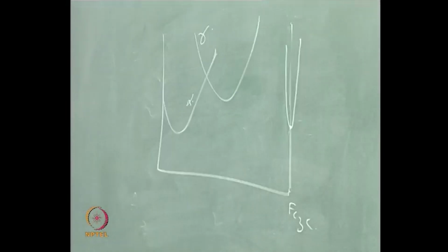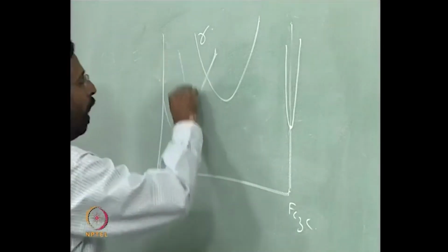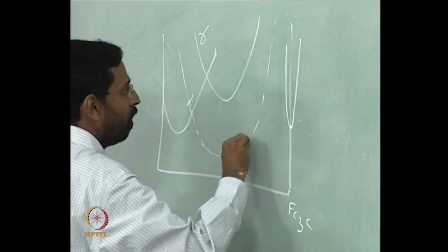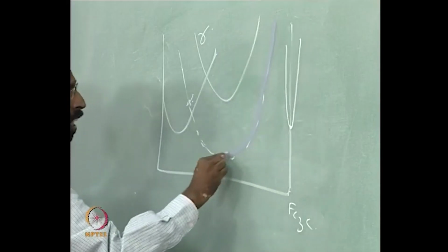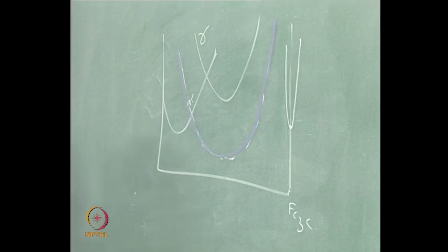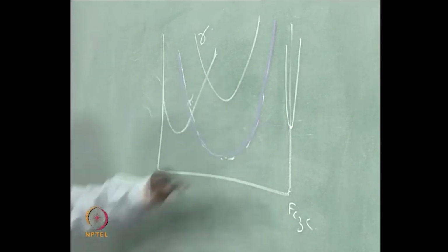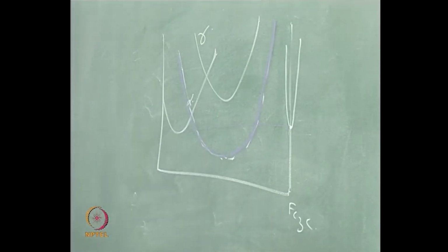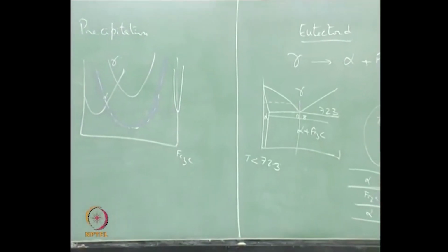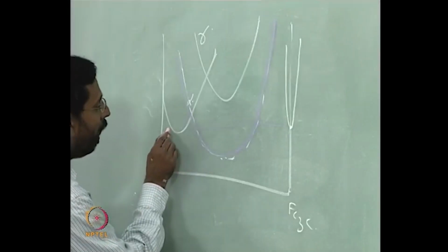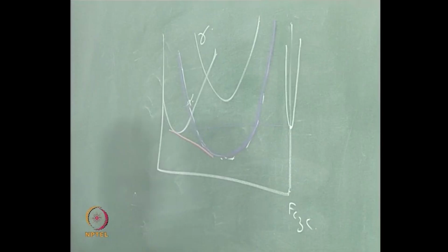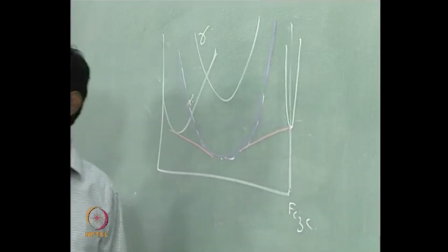If I am at a temperature higher than 723, then what should happen? Then austenite, so the austenite free energy curve will be below. So you would have a situation something like this, a curve like this, and then if I draw a common tangent between these two, the common tangent between those two is going to be higher than the free energy curve of gamma. As a result, if the same alloy I heat to a higher temperature, then at that temperature in principle I would have a common tangent between alpha and gamma, and another common tangent between gamma and Fe3C, and